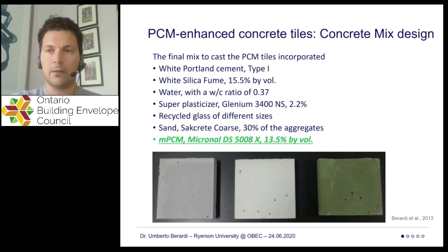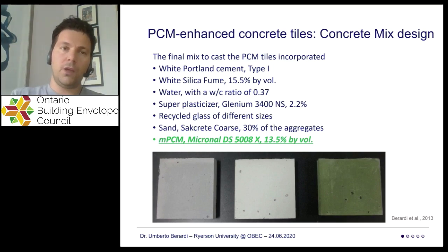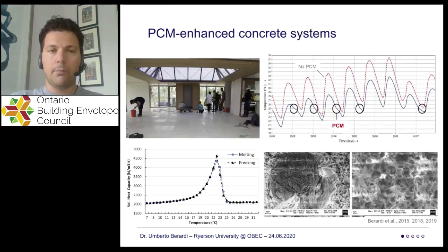And we mixed this powder at 13% by volume in the concrete tiles that were used for the pavement of the house. So if you see on the top left image in this slide, you see these concrete tiles. They were basically put at the end of this lightweight construction, fully glazed. So a house that was taking significant risk of being extremely hot in the middle of a sunny day.